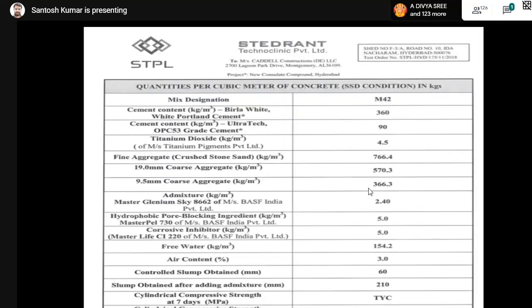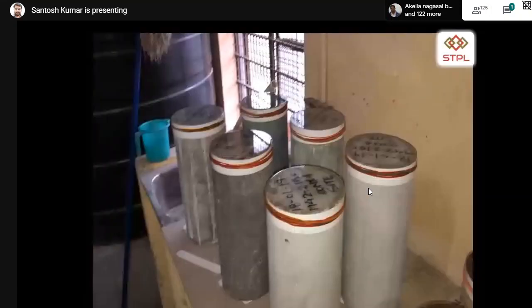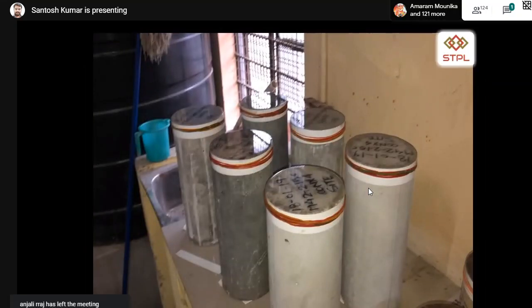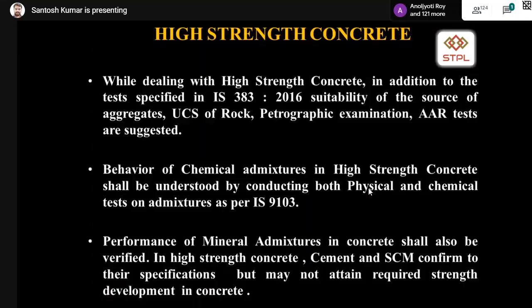We have used grey cement, white cement, titanium dioxide, fine aggregate, 19 mm and 9 mm aggregate, and admixtures, waterproofing chemicals, corrosion inhibitors, many things we have used in one single mix design. And you can see the cylinders on the right side of the photograph, the white concrete looks fair enough that there is not even a single pop out on the cylinder sample. This is how the concrete is constructed in the US Consulate in Hyderabad.